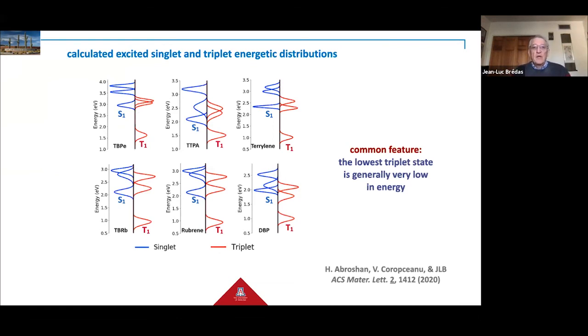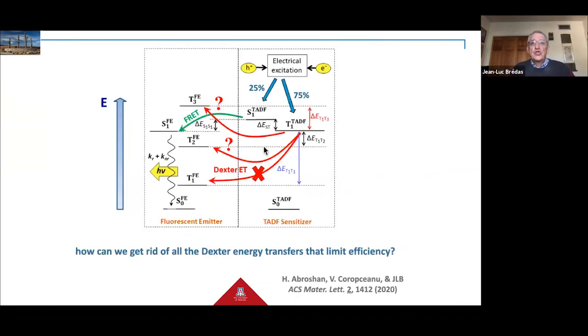And so what it means is that when we go back to the energy state diagrams, with the TADF sensitizers to the right and the fluorescent emitters to the left, the Dexter energy transfer, which we want to prevent, from the lowest triplet of the sensitizer to the lowest triplet of the emitter will be negligible, because of that large difference in energy, we are in a Marcus inverted regime. But there is still the possibility of Dexter energy transfer to upper-lying triplet excited states on the emitter.